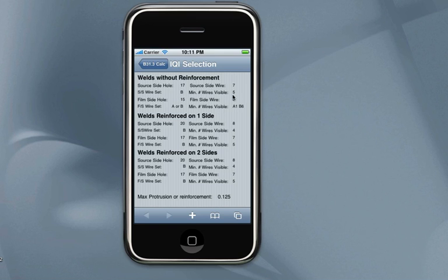This minimum number of wires is not one you see in the code, but you know that essential wire, like the number 7 in this case, that means that in that B set you would have to be able to see 5 wires. If you couldn't count 5 wires on the film, you wouldn't be looking at the proper wire. If there's 6 wires in the set, what that's saying is you have to be able to see at least 5 of those to be the proper, this number 7 here.